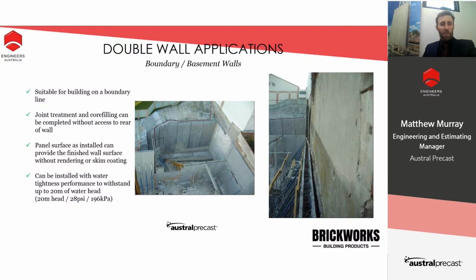When it comes to building with double wall, putting these panels on the boundary line is a very significant advantage in comparison to other methods. And the fact that we can core fill the panels and apply waterproofing at the joint means that the spacing required to the boundary can be significantly reduced, really increasing the speed and reducing the time of construction on site for the contractor. The water tightness that we can achieve is up to 20 meters of waterhead, just for interest.